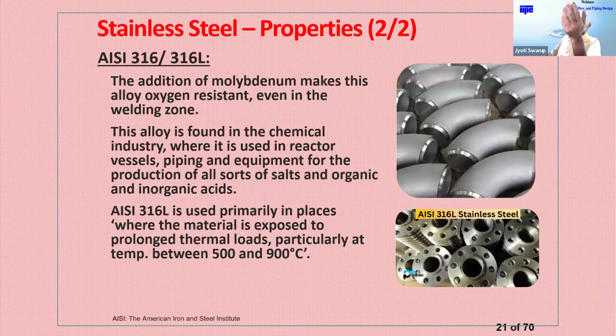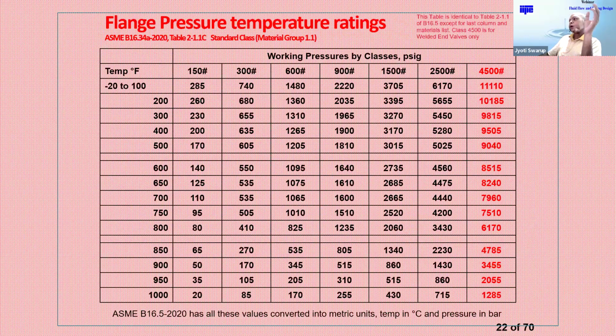Now 316 or 316L is definitely more expensive than 304, and definitely 4 or 5 times costlier than the carbon steel material. Therefore, 316L is selected only when there is a real requirement for high resistance to corrosion. And of course, many clients use 316 or 316L where material is exposed to prolonged thermal loads, particularly high temperature, 500 to 900 degrees centigrade. So there are other criteria for material selection, but as I said, it is always the lowest cost material which needs to be selected to optimize the project cost, and not a size or material which is more than required or less than required.